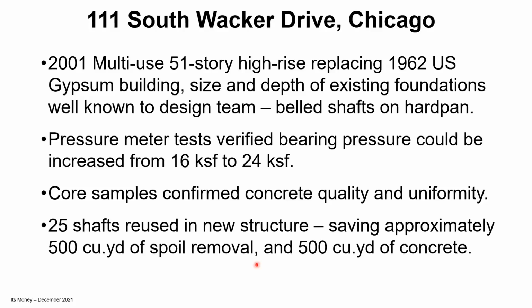So approximately 500 cubic yards of spoil didn't have to be removed and 500 yards of concrete didn't have to be trucked in. So there again is a huge environmental saving in a city with traffic as dense as Chicago's. Not having to use all those truckloads of material was significant. The final structure also reused the perimeter wall and caissons from the parking structure, and the total savings for the project was about $1 million, which apparently in the design phase turned out to be the critical factor as to whether the thing would be built or not.